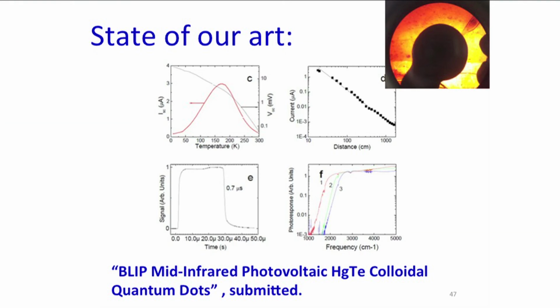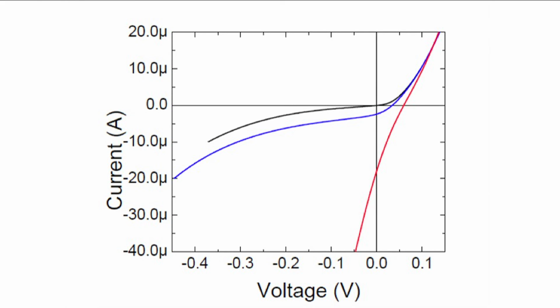The devices are fast, about microsecond time response, not unexpected given the mobility. They're linear, which is a nice thing about photovoltaic devices. The response is linear with power, and that's important when you do imaging. And they can be tuned by just changing the size of the particle, so that's pretty nice. And this shows the last data slide.